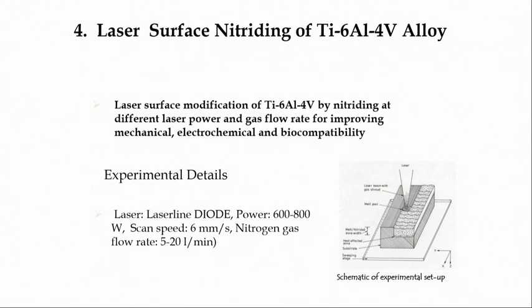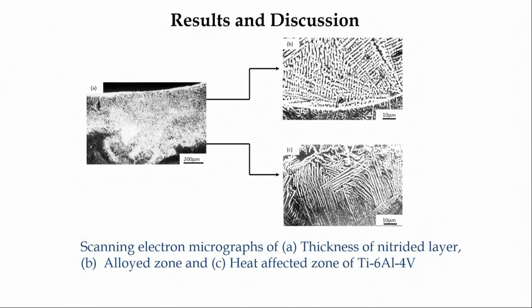This particular treatment may be termed under surface alloying, but may be under chemical conversion coating also, because instead of heating you are using the melting phenomena and nitrogen shroud to form nitride layer on the surface. So, this is such an example where high power laser beam was used to melt the surface of titanium, and where nitrogen shrouding environment was applied. You see that on the surface of titanium there was formation of very thin, not monolithic, but dispersed nitride layer. If you see the surface carefully, you will find that there are a lot of dendrites containing the nitrides, titanium nitrides, and also the continuous and defect free solid liquid interface, where nothing was present.